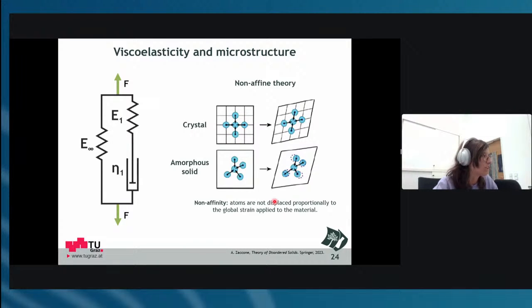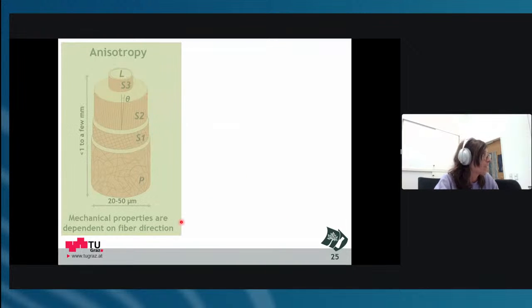When I test at a very low frequency, of course, the atoms have more time, and they have more of this non-affine movement. But when I test very quickly, this is inhibited. So it's kind of the same. I would say it's a materials perspective and also a mechanical perspective, which is a possible explanation, but this needs much further looking into. There is not much literature out there which really compares mechanical testing to Brillouin testing. Just in the life sciences, they focus a lot on the comparison between AFM and Brillouin, but that is another story. So I've finished with that, and now I'm seeing that I'm really slow.